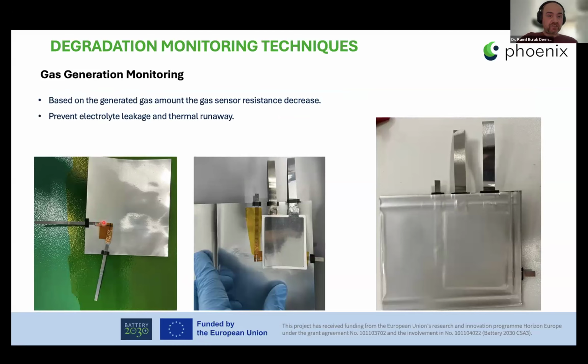Another monitoring technique is gas generation monitoring. Based on the generated gas amount, the gas sensor resistance is decreasing. So this also helps prevent electrolyte leakage and thermal runaway. As said, the gas is not wanted in the battery chemistry, so we have to detect it and remove it if possible, but it is also inevitable because it is a part of the chemistry underneath. Therefore, we placed our gas monitoring sensors just next to the cells, so that if gas is generated between the stack, we will be able to capture it. That's the PHOENIX way of capturing the gas.